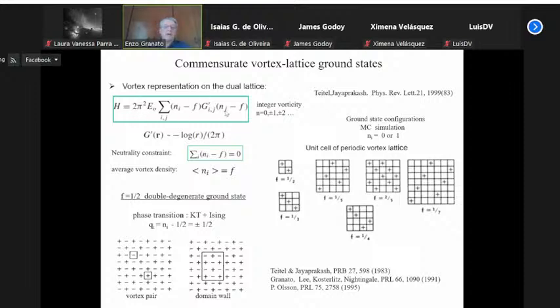So if you use this Hamiltonian to find the ground state configuration of the vortices, for example, for square lattices, these are the configurations we find for the ground state. For f equal to 1/2, we have one vortex, indicated here by plus, in every other plaquette. And you can already see that it is doubly degenerate because you can have a plus and plus diagonal here, or plus and plus diagonal here, with no vortex here. And for other values of f, you have a more complicated ground state, and the degeneracy of the ground state is related to the denominator of this frustration parameter. As a result of these different ground states as a function of f, there's a sharp variation of the system behavior as a function of the magnetic field.